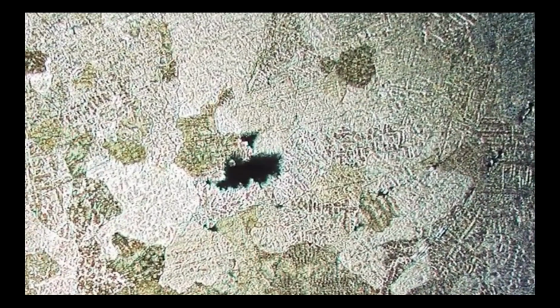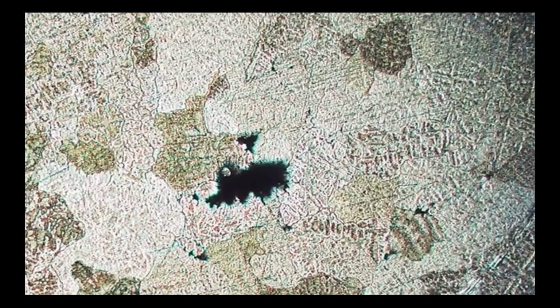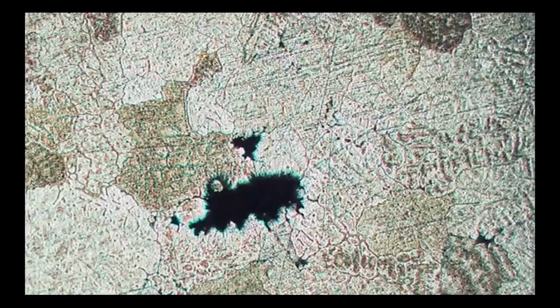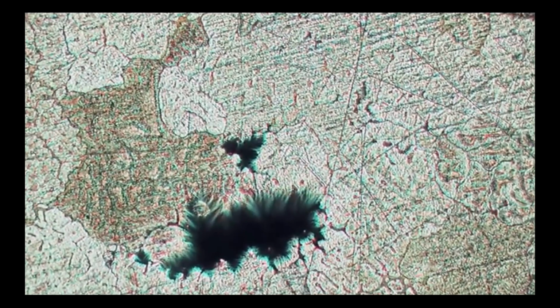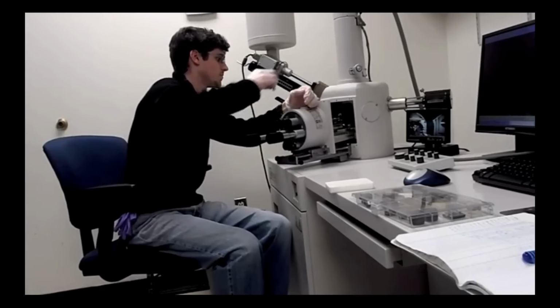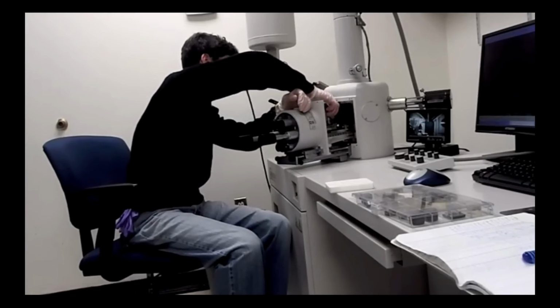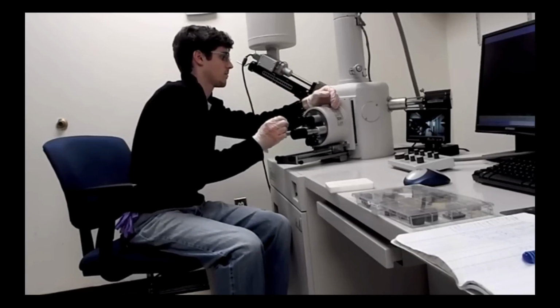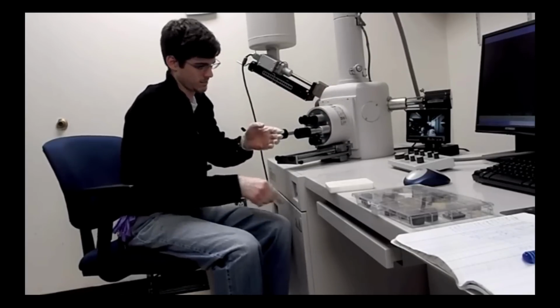As we increase the magnification on this sample of polished and etched aluminum, we can begin to see the defects where corrosion initiates. They're the black voids, the gray dendrites, and these dark second phase particles. We're going to put our corroded aluminum sample into an electron microscope and get higher magnification images of the corroded surface.